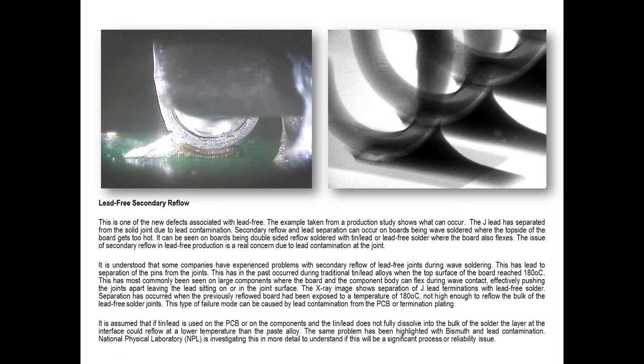That's classic secondary reflow. The other form of secondary reflow is where you've got a mixture of lead-free and tin lead. Or to be more accurate, if you've got component terminations which have got lead on them, so typical tin lead, so 90% tin, 10% lead. If you solder those with lead free, again, you can make some perfectly good, reliable joints. But you have to bear in mind that the solder interface that you've created between that mixture with the lead contamination in the joint, and the same thing can happen with other alloys, is that the actual reflow temperature of that joint will be equal to or lower than the material you're actually using. So with lead free, the actual temperature that joint would reflow for the second time would be more like tin lead reflow temperature.